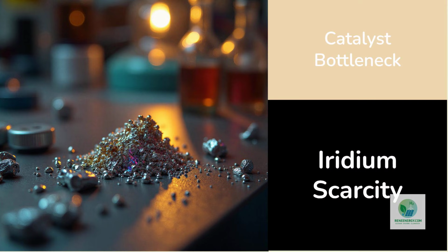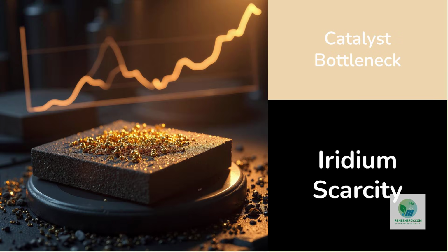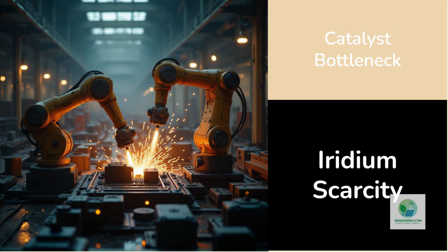Now, consider catalysts, specifically iridium, the costliest component of a PEM electrolyzer. Iridium is one of the rarest materials on Earth. The global supply is a few tons per year. Prices fluctuate between $150,000 and $200,000 per kilogram. Until recently, PEM electrolyzer anodes required iridium loadings of 2 to 4 milligrams per square centimeter. That made catalysts one of the most expensive parts of the entire stack, and it limited global scaling.